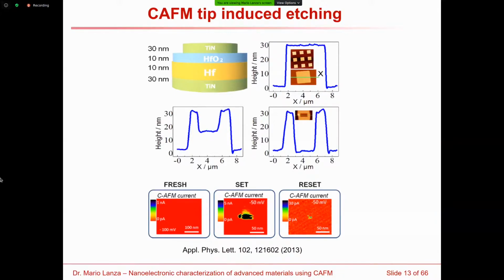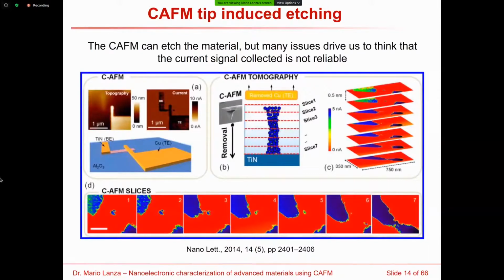However, in 2014, some people noticed that the tip could also be used to etch the bulk of the dielectric and observe how the size of these filaments evolves with the depth inside this dielectric. So this was done in the past, and people could make three-dimensional current maps of these dielectrics. For example, in this work, one of my colleagues in IMEC performed this three-dimensional characterization of one single conductive filament by applying one electrical stress and then mechanical stress to etch, and then electrical stress to read, and then mechanical stress to etch. And like this, he made 7 slices, and he rendered them three-dimensionally, and he could make this beautiful study.